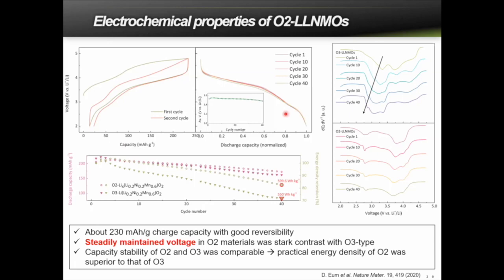In comparison with the conventional O3 type structure sample, as we can see here, they show a gradual decay of the voltage over 40 cycles, but our sample shows steady voltage at high voltage here. And because of the suppressed voltage decay, the practical energy density of O2 was very well retained. It is about 600 watt hours per kilogram after 40 cycles, which is superior to that of the O3 type structure.